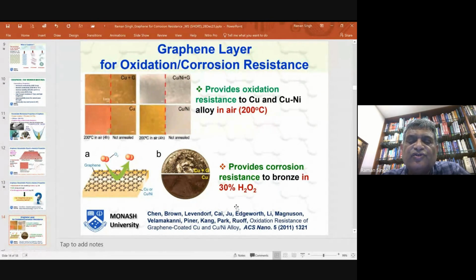Rod Ruoff's group from Texas took pure copper and graphene coated copper, and exposed them to air at 200 degrees Celsius, and they found that pure copper oxidized. That's why the change in color. The graphene coated one did not oxidize. They did a similar experiment on copper nickel alloy, and found that the copper nickel alloy did change color. The graphene coated one did not change color.